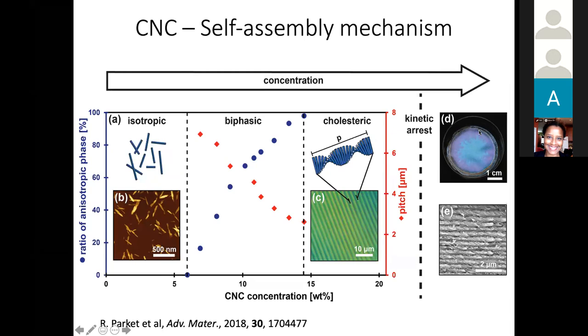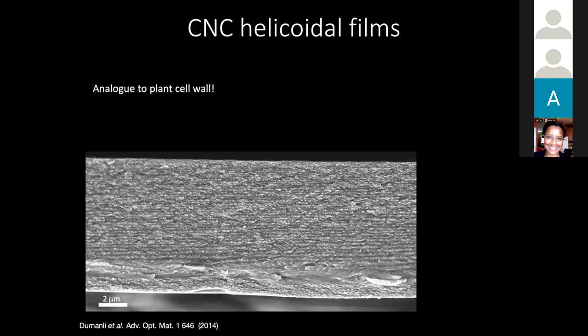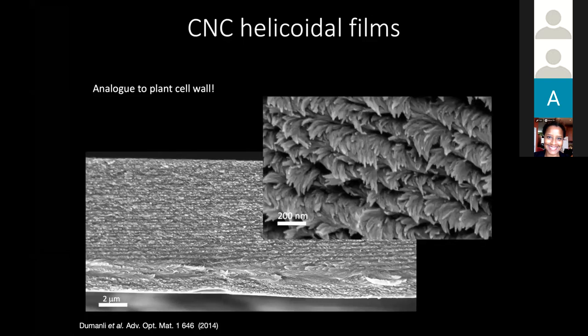And in fact, when you dry it out and you make a film out of it, this architecture can be maintained and you obtain color in exactly the same way as what you have in plants, using essentially the same material. So just to give you another slide to convince you, this is an SEM picture cross section. Now, not anymore of the fruits, but if you recall the one that I showed you a few slides ago, it is essentially really analogous. Also here, you can really see this small crystalline structure that essentially rotates and twists. And this twist is essentially coming from the orientation of this cellulose nanocrystal that goes layer by layer. And again, if the dimensionality is right, you can change the coloration.